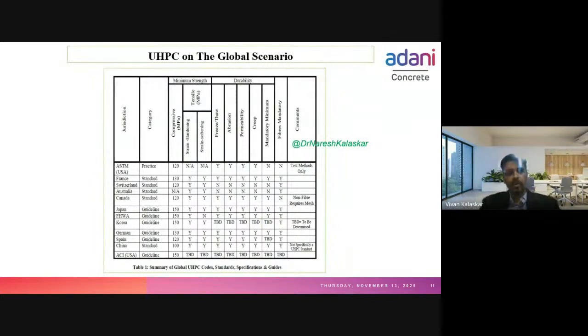If you see UHPC in the global scenario, in India we don't have any UHPC code, but in each country they have defined UHPC in a different way. In China, they have defined UHPC as a minimum compressive strength of 100 MPa. In Canada, they have defined UHPC as 120 MPa minimum compressive strength. The ACI code defines 150 MPa as the minimum strength for UHPC. In India, we don't have any UHPC code, and we have guidelines only up to M80. So in this research, we have developed UHPC from M80 to M150 to bridge the gap from Indian standard M80, M90. That's the reason M80 and M90 also have been designed in this project.